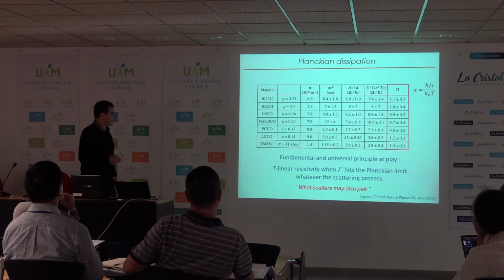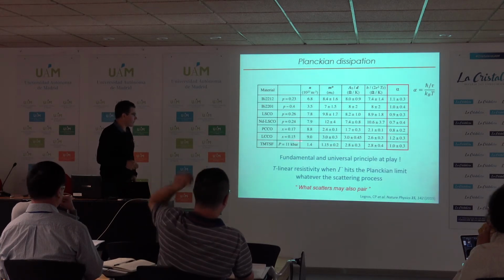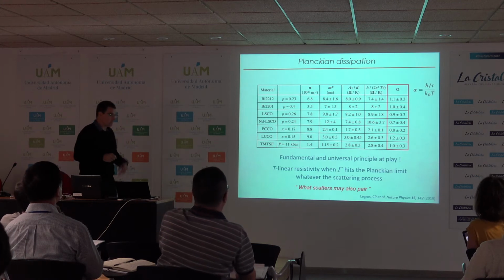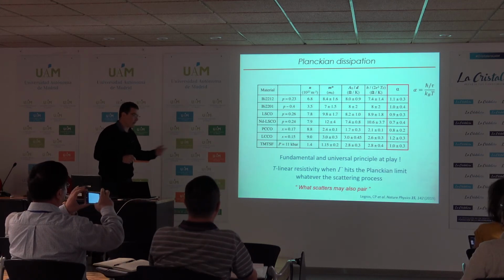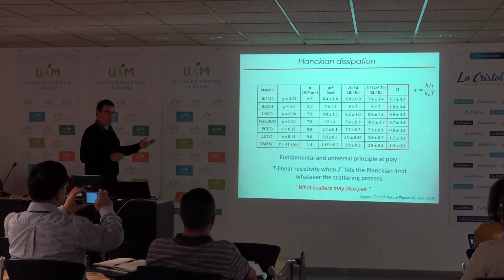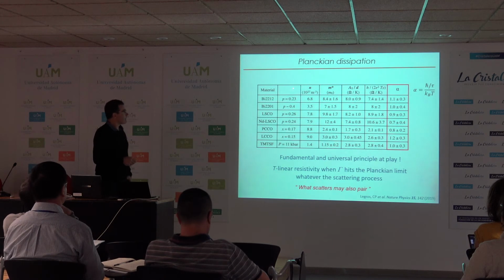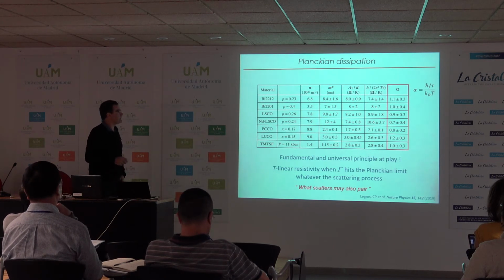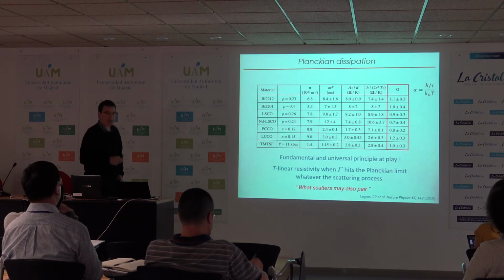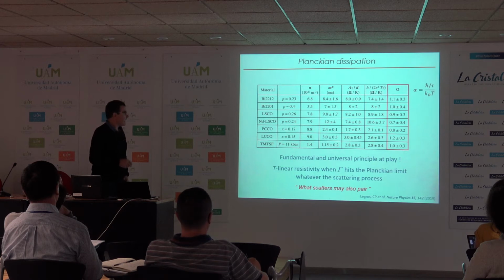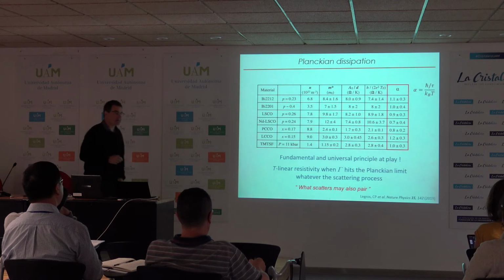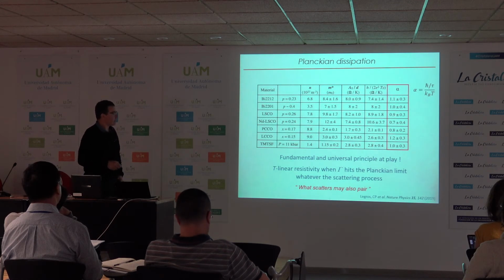And the case is very compelling for the electron-doped cuprate, because both the quantum oscillations, that is to say the density of carriers, and the effective mass have been measured directly experimentally. Here in this table, which you can find in this paper, we have compiled the density of carriers and the effective mass, here measured by quantum oscillation. For the hole-doped cuprate, we have deduced the effective mass from specific heat measurements. And if you look at the alpha coefficient, where alpha equals 1 for the Planckian dissipation, you see that this is almost 1, plus or minus 30-40% depending on the family.